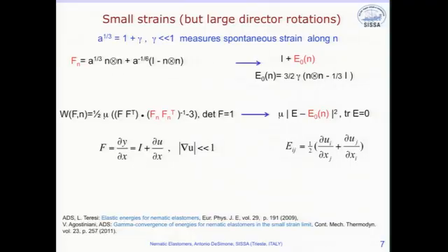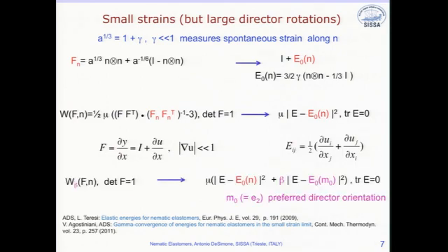So this is the expression. So it's a positive constant, the shear modulus, times a quantity which is non-negative, because it's a square, and it's 0 if and only if this is 0. So it's 0 if and only if the strain of linear elasticity, so the symmetric part of the displacement gradient, equals the spontaneous strain. So it's very easy to see when this is 0, right? When this equals that. Okay. This is the geometric structure of the linear theory. Okay. You can do the same thing with the beta perturbation, and what happens is that you get another term with the same structure, but with a beta in front. Okay. And I will discuss this in a second.